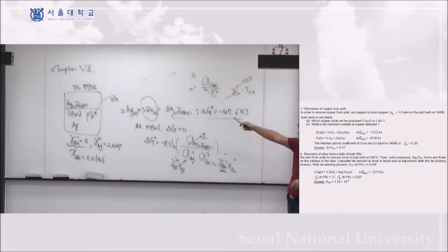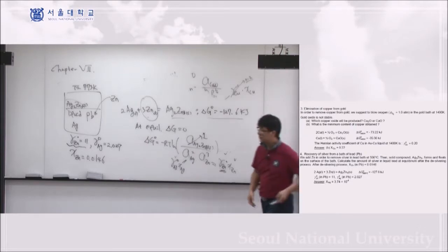Once you take out Ag2Zn3, then you remelt it. You're melting it again, and Zn has a very high vapor pressure. So if you increase the temperature, Zn will evaporate by itself, and you get high quality silver easily in the end. And also, if you're adding oxygen, Zn will like to form the oxide too. So it's easy too.